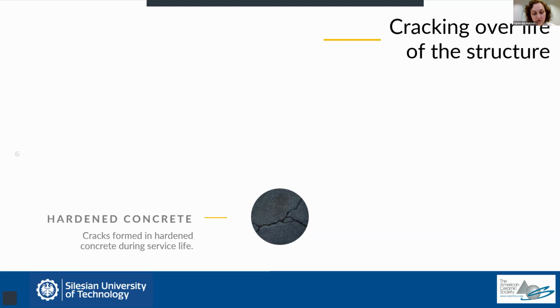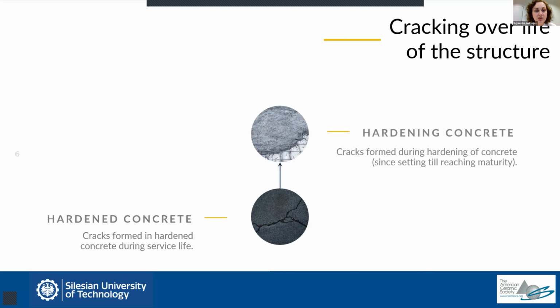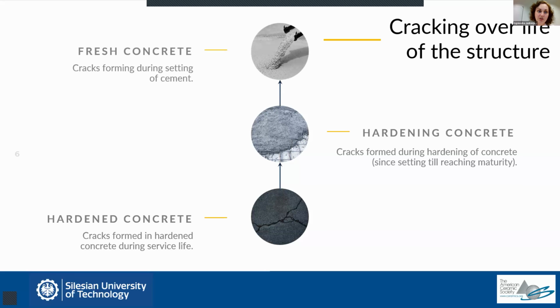However, what most engineers don't realize or neglect is that cracks can appear much earlier during the life of the structure. One of the very important problems related to cracking are cracks which occur during the hardening phase in concrete, so between setting and maturity, as well as the cracks that can happen already in fresh concrete during setting.